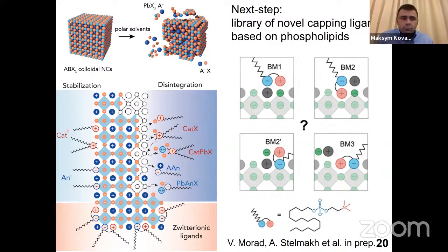And so now we started to ask ourselves, do we really understand fully how these ligands actually attach to the surface, these zwitterionic ligands? And because of our new synthesis, we thought if we better understand how the ligands attach, then it will give us some design rules for how to engineer the head groups and the tails. And then we can attach all kinds of phospholipids to our nanocrystals and check the whole library of them.